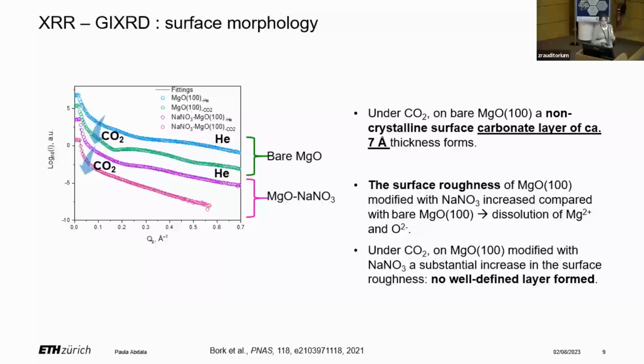Now, when we promote this material with sodium nitrate, we cover it completely. And the first observation is that the surface became rougher. So this tells us that it's likely that the sodium nitrate is etching the surface, dissolving the magnesium oxide surface. And when we flow CO2 over this material, there is a complete loss of a layer. We don't observe a layer, and it's a rough surface. So it's unlikely that magnesium carbonate grows as a layer when we add the promoter.